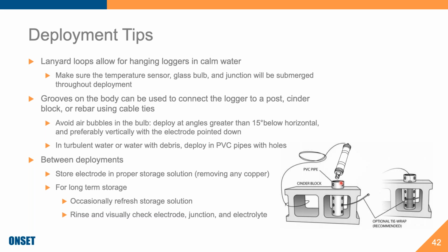Another option, if you're storing it for an extremely long time, one option I've seen recommended, and I'm not 100% sold on it, is to store it dry, meaning you just take your electrode out of any storage solution. That was one manufacturer's recommendation, and I'm not sure I would actually recommend that too much, but it is an option, especially if the manufacturer for that electrode says to do it, then by all means, maybe follow that. But that's for an extended period of time, like several months or the majority of a year. If you store it dry, then it should be okay, and you're saving the electrolyte essentially. But then you'll want to definitely recondition by soaking it in a storage solution for, I would argue, a couple of days before deployment.